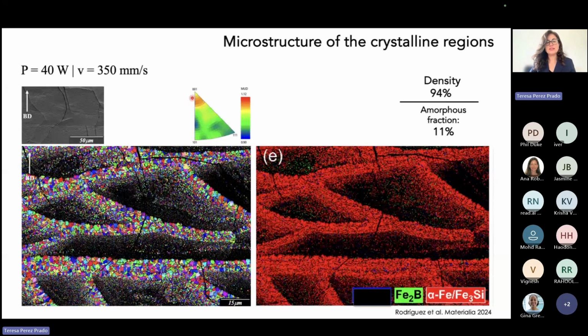If we zoom in a little bit using EBSD, in the same sample, here on the left we have an inverse pole figure map, and the colors correspond to the orientation of the build direction according to this color coding. But you can see by the diversity of colors that we have a randomly oriented microstructure. The crystallites are equiaxed, with sizes of about 3-4 microns and below. And here to the right is a phase map where most of it is red, meaning that most of it is iron-silicon crystals. There is only a minor fraction, I don't know if it can be seen, these green dots here, which correspond to a minor fraction of borides. But this is how our composite looks like.